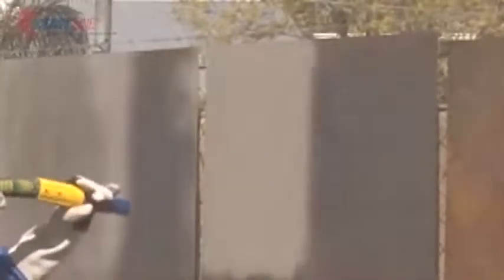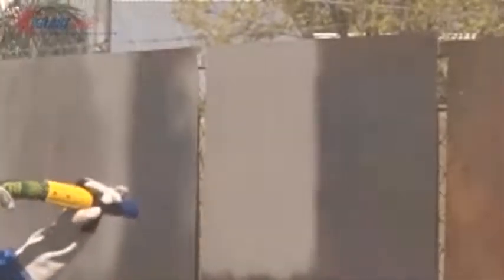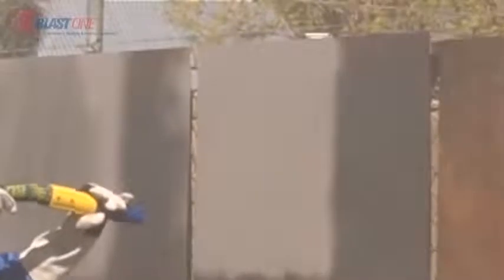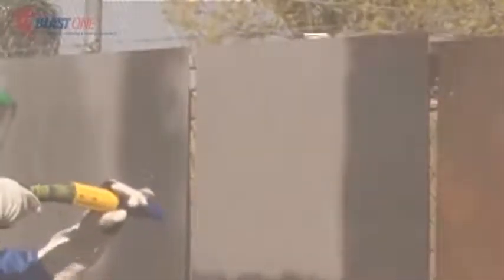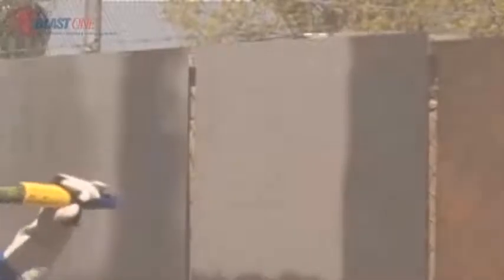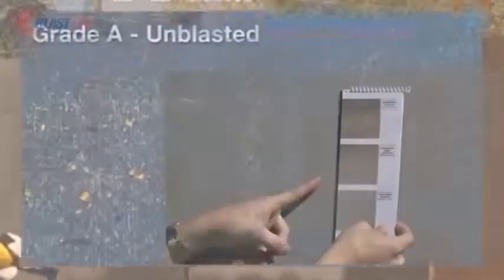A lot of dust is caused by rust being on the steel. In this example, there is no rust to create dust, and also the abrasive being used is Speed Blast Australian Garnet, which is a very hard, cost-effective particle which can blast quickly and causes little dust. It is highly recommended when blasting grade A mill scale surfaces.